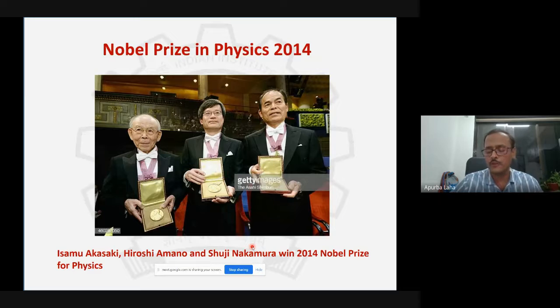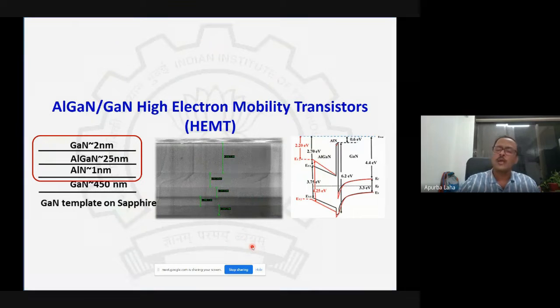Now there's a lot of revolution that has happened. Quickly, to the other side of these gallium nitride materials: it's unique, as I said. All you have to do is make a heterostructure. For example, here, you see a heterostructure which comprises a single crystalline gallium nitride layer, and then on the top you put aluminum mixed with the gallium, and then another thin layer of that.